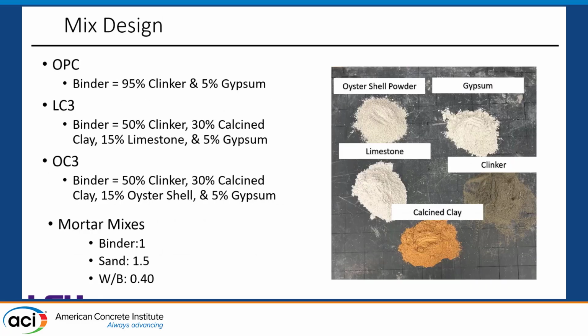So we used 3 different binders to test in this experiment. One was just an ordinary Portland cement binder that just used clinker and gypsum. A second one was LC3, using that same mix design that I discussed earlier on the first few slides. And then a third one that replaced all of the limestone used in LC3 with completely oyster shell. We had a ratio with our mortar mixes of 1 binder to 1.5 sand and a water to binder ratio of 0.4.